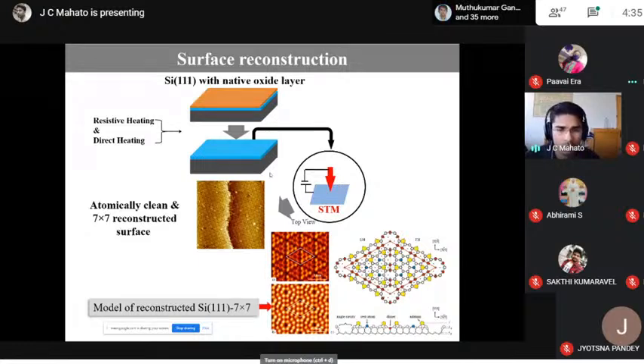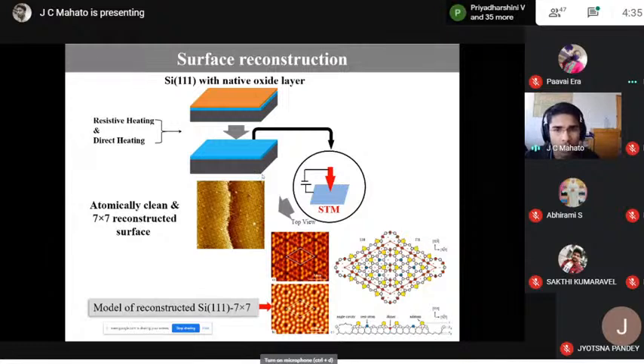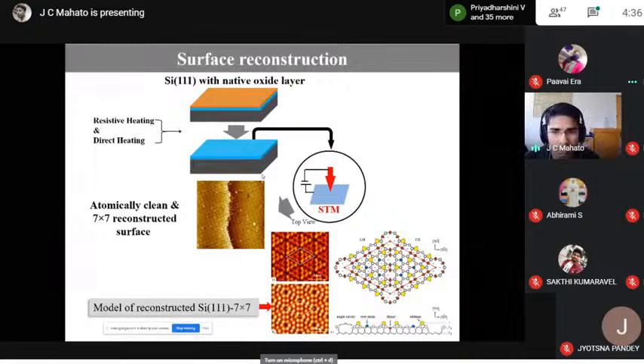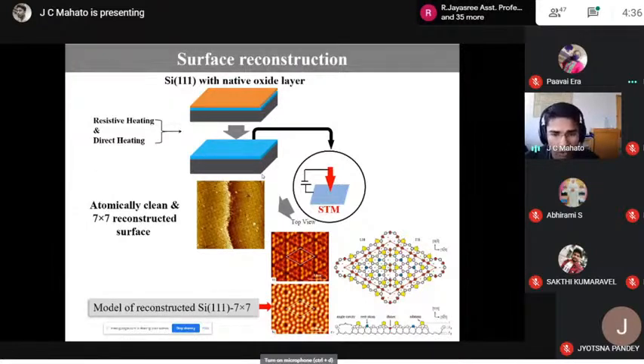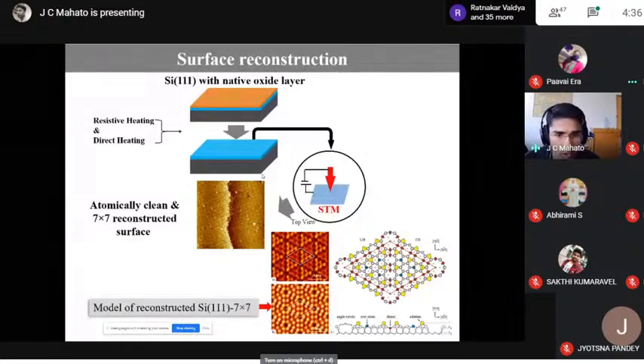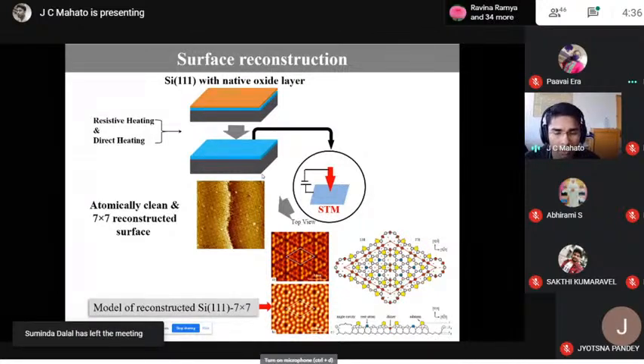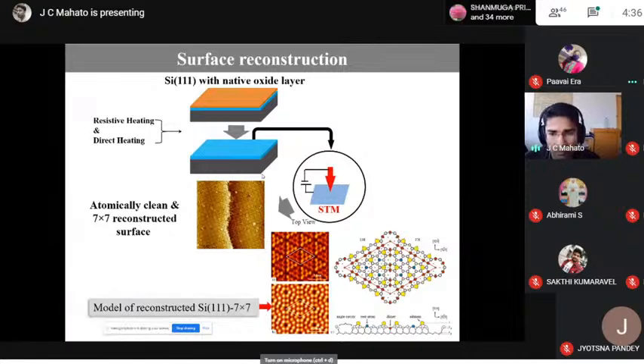When we raise the temperature of the silicon wafer to 1250 degrees, the oxide layer gets removed. And then we bring down the temperature to 870 degrees Celsius, where the top layer atoms rearrange themselves to get a minimum energy configuration. This new rearrangement phenomenon is called surface reconstruction. So we found that in silicon 111, the 7 by 7 reconstruction is the lowest energy reconstruction of the 111 surface. That means the surface unit cell is 7 times larger than the bulk ideal 1 by 1 unit cell of silicon.